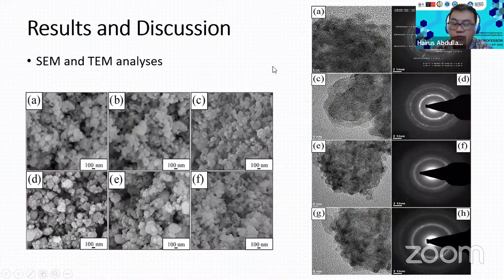Then we also briefly take the SEM and TEM analysis. All the nanoparticle sizes are quite similar, around 100 nanometers. The very interesting result here is what we can see from the SAED pattern, the selected area electron diffraction pattern. The interesting thing here is the broad ring pattern, right? The broad ring pattern.